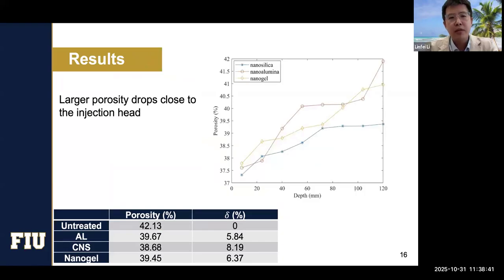So, some preliminary data we got from that. As you can see, we did the same thing. We drew a core from the sample, cut it into slices, and measured the porosity. We got a pretty similar trend, relatively consistent across different types of nanomaterials. For example, we have a porosity of 42.13%, and with alumina colloidal nanosilica nanogel, we see some porosity decrease. And then of course we calculate the relative porosity change. We didn't do much with that until the project ended, but since we measured the porosity, I think it's partially a success of this project.